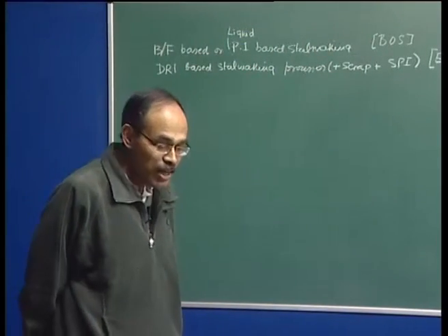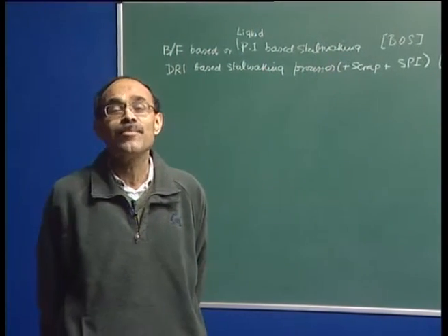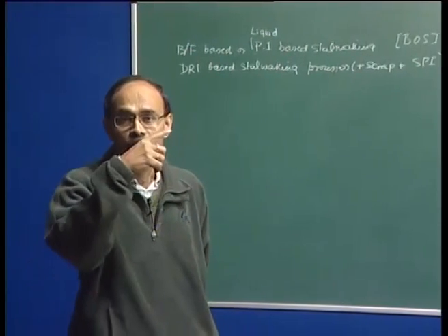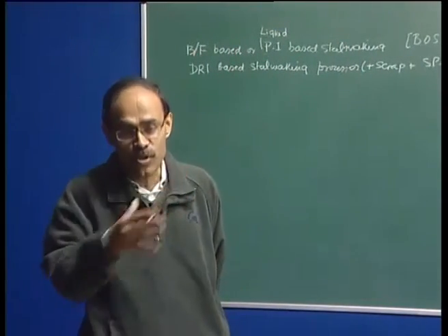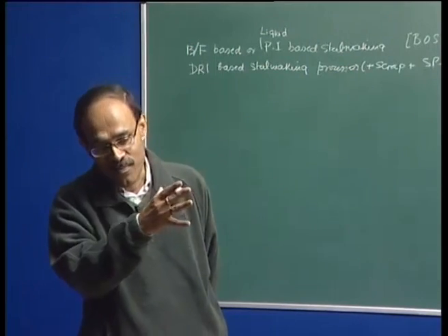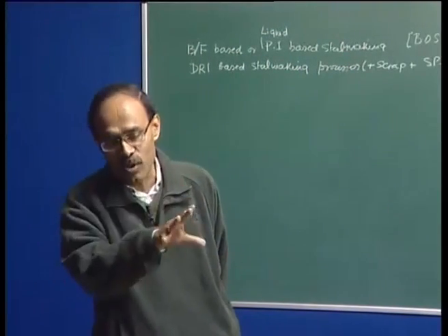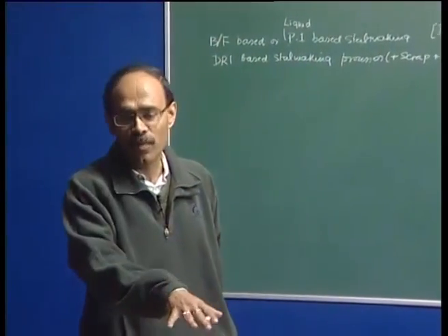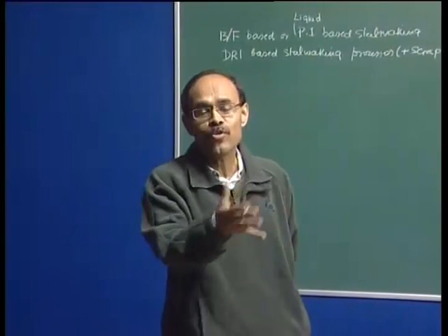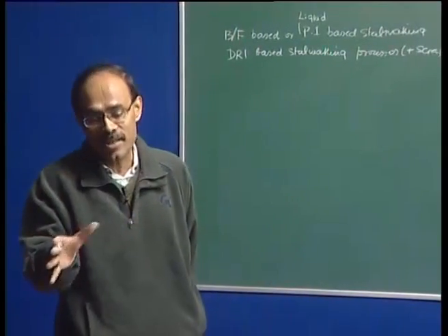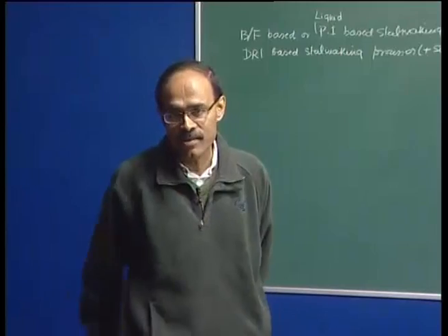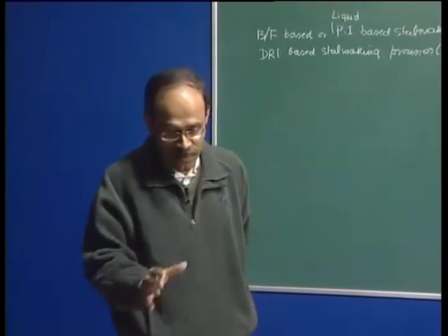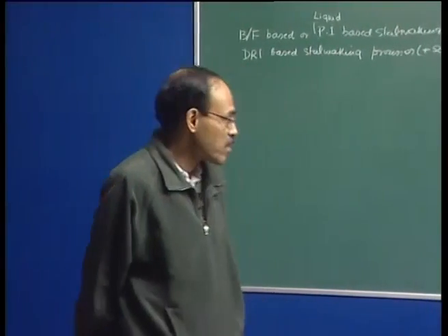Today, a steel plant based on ingot casting with BOF steel making is not sustainable at all, because the rate at which the basic oxygen steel making process produces steel, it requires an equally fast process to convert molten steel into solid product. Ingot casting is a much slower process. The conversion rate from liquid to solid is much slower in ingot casting than in continuous casting. So, ingot casting is no match for BOS. So, with BOS or BOF, we require continuous casting of steel.